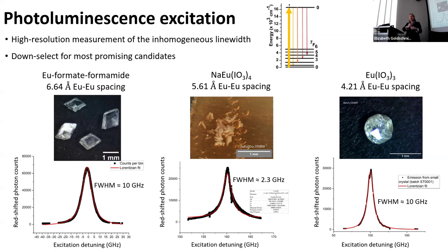Our lithium niobate, similarly, the erbium is incorporated during growth, and then it gets smart cut and turned into a thin film. Here, we're obviously growing in solution. We're incorporating the europium. You can also do ion implantation into an existing material. You tend to end up with worse properties if you do that instead of incorporating during growth, because you kind of add more defects, right? But it's not crazy. So people do both.